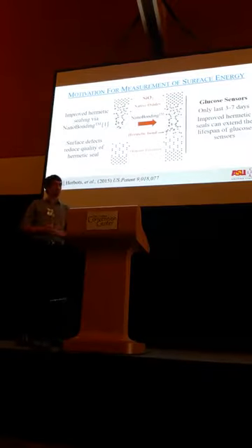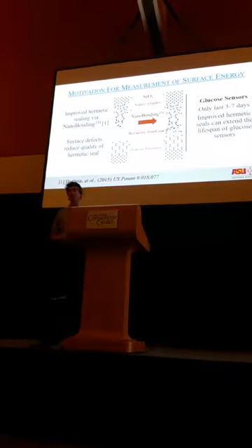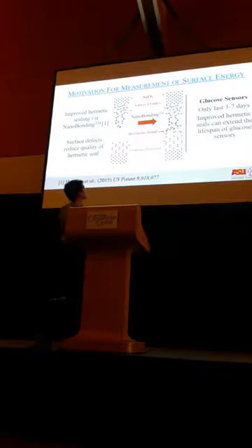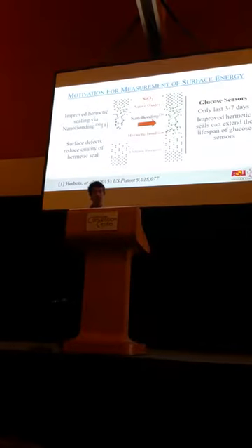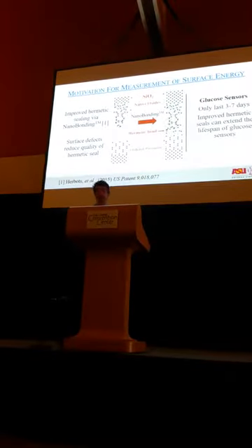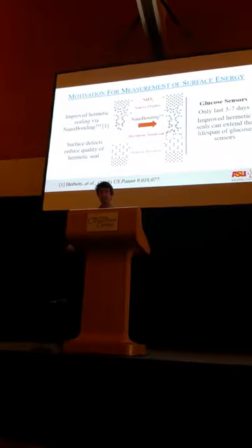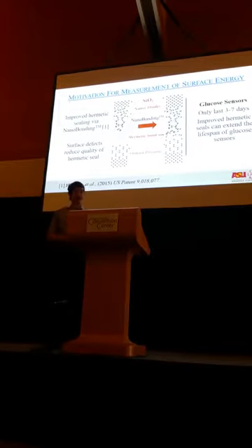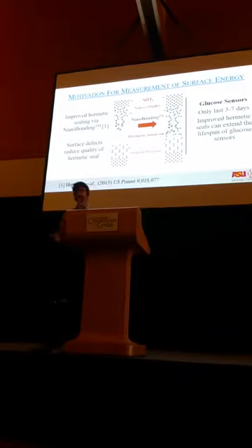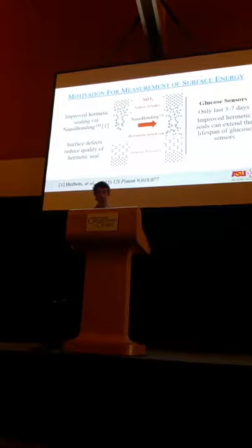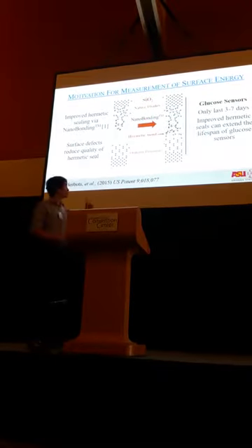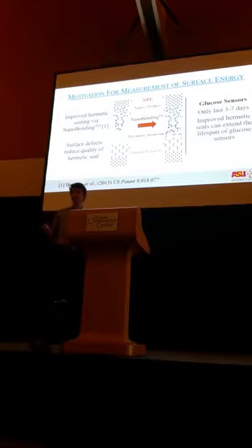The surface energy of a material scales with the surface roughness of the native oxides that grow on the surface, these native oxides here. The surface roughness corresponds to the number of defects, dangling bonds, and impurities in the native oxides. The presence of these defects negatively impacts hermetic seals by allowing for fluid percolation and ion diffusion when they are exposed to saline environments. For this reason, hermetically sealed electronic sensors must be replaced after a relatively short period of time. For example, glucose sensors only last about a week in the human body.